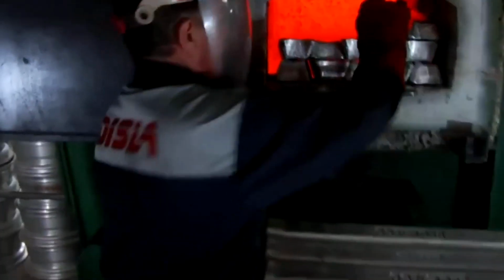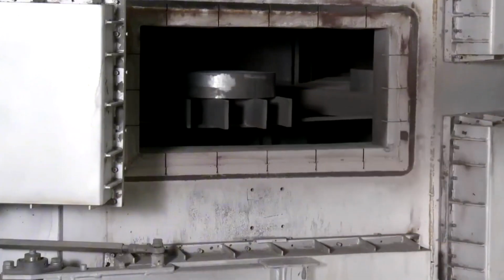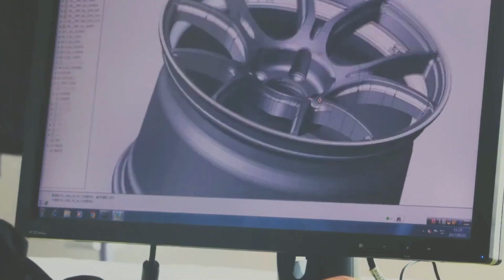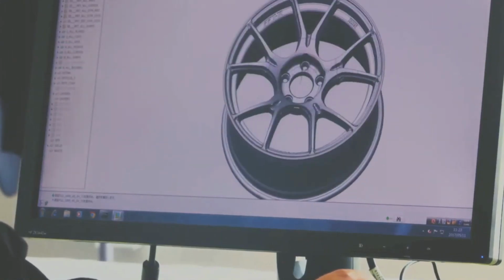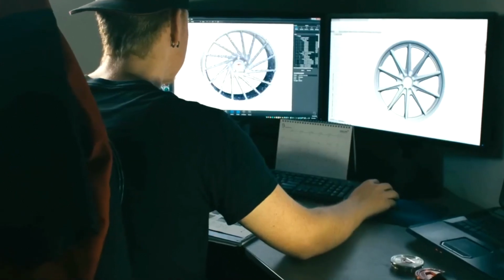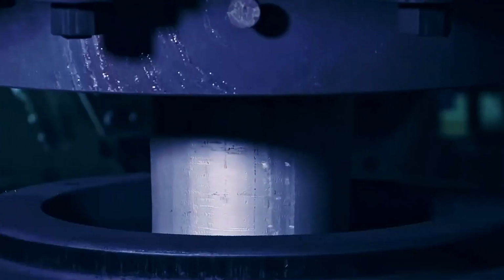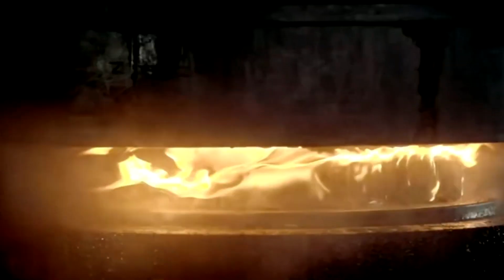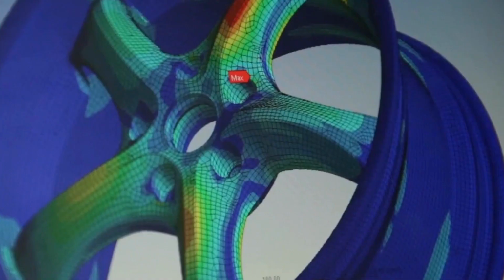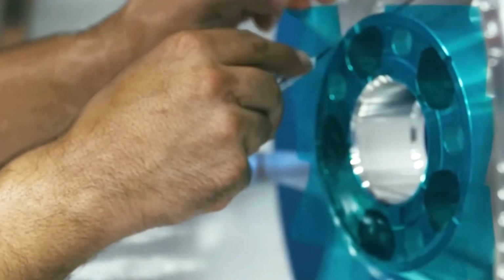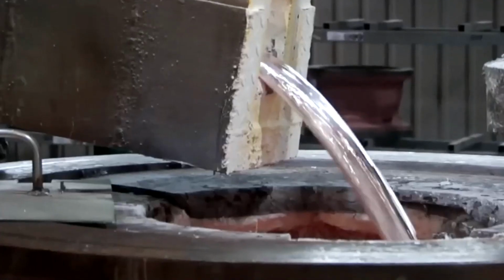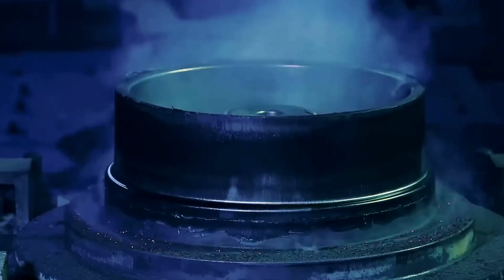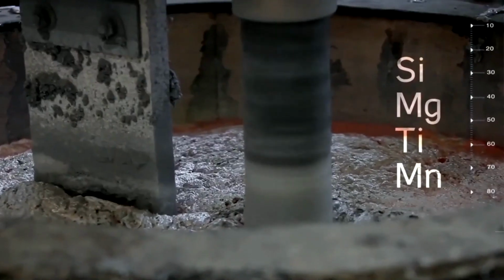It is heated until it reaches a plastic, workable state, and when the required temperature is reached, each billet is placed onto a die. It is subjected to the force of a massive hydraulic press, often between 6,000 and 10,000 tons. Under this pressure, the internal grain structure of the metal is compacted and realigned along the direction of force. This action eliminates gas pockets, micro cracks, and the defects commonly found in cast material. The result is a forged wheel blank, with mechanical strength increased by as much as 30 to 40% compared to a cast wheel, while also being noticeably lighter.